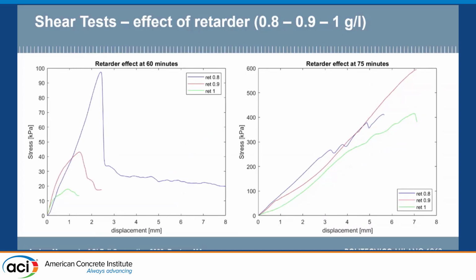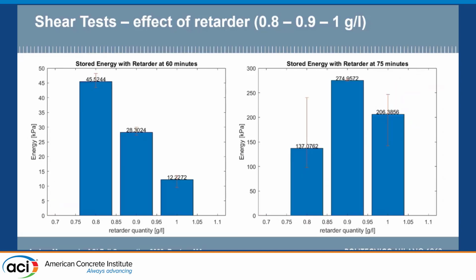This is the influence of the retarder. So at 60 minutes, we can see a clear dependency of the strength on the retarder. As a matter of fact, the higher the retarder, the lower the strength. Whereas at 75 minutes, we no longer have the effect of the retarder on the development of the strength. In fact, as you can see from the curves, they are pretty much close to each other.